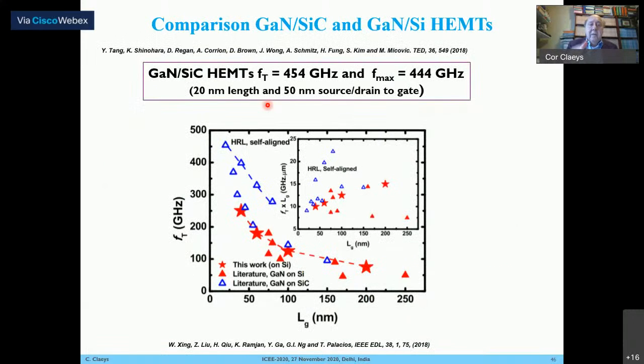Can we compete with gallium nitride on silicon carbide? The answer for the moment is no, because the best device reported for gallium nitride on silicon carbide has an FT and an Fmax of 450 gigahertz. However, if you look at the evolution, FT versus the gate length, and if you look at the blue data, that's for gallium nitride on silicon carbide, but if you look at the red data for gallium nitride on silicon, then you see that the frequency performance is coming closer to the one that we got for gallium nitride on silicon carbide.